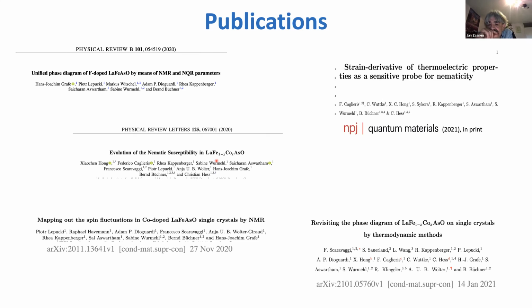So nematic susceptibility, when it gets large enough, the lattice couples in and promotes the transition to a first order, while by itself it would be a second order, right? It's Curie-Weiss. And when you have the first order transition and the lattice is coupled in, the lattice is talking in a very different way with this order than the electron system is doing. Right? The electrons are kind of self-annealing things.